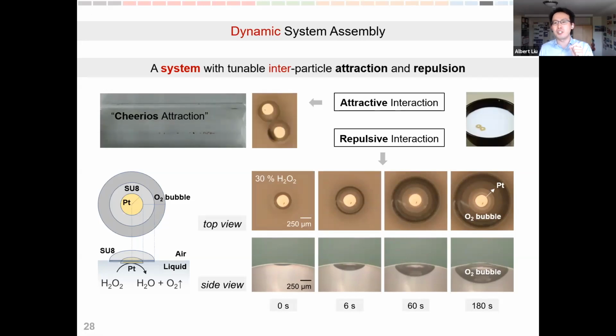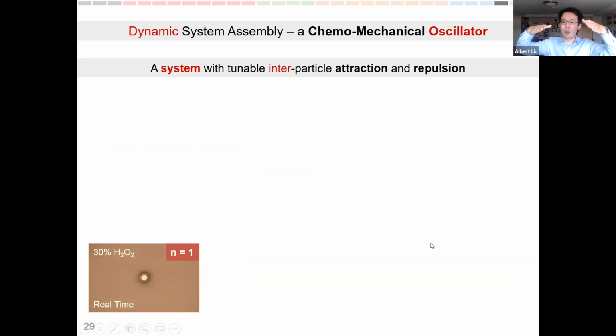I should tell you one additional piece of information here. As particles are arrested at the air-water interface, they are subjected to a capillary interaction that is broadly known as Cheerios attraction, for the very reason that it's responsible for the fact that Cheerios will always come together in your breakfast milk bowl. So this Cheerios attraction between two particles can serve as an interparticle attractive force that will drive these particles together. While this one single particle, as it's arrested at the air-water interface, doesn't do much, it reaches basically an equilibrium phase where the bubble production rate dramatically slows down.